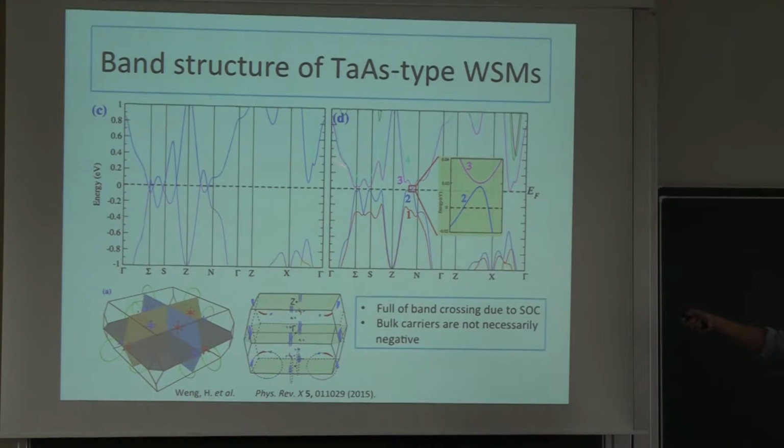That means in this material, there are a lot of band crossings. Actually, these band crossing points in k-space form a ring, a nodal ring. Along this ring everywhere, the band gap is 0 without spin-orbit coupling. Spin-orbit coupling simply gaps this ring out. Then at some low symmetry points, we get the Weyl points. From the band structure, we already see there are a lot of band crossings.